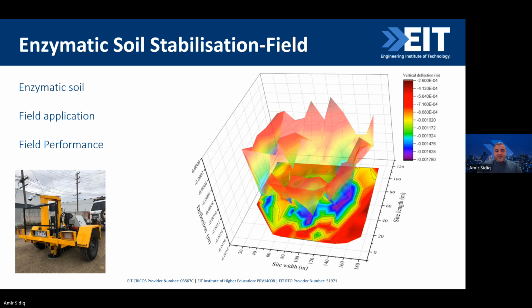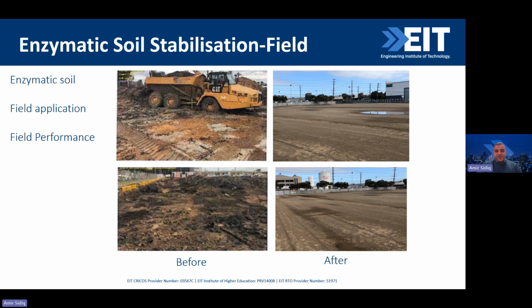So that was the existing conditions. You can see this particular construction vehicle is almost stuck because of the clay behavior, and then after stabilization it becomes nice and smooth. It looks solid, and I did pass by this site a couple of times, and they actually used a crane in this area for the construction. So without the base, it was very strong.